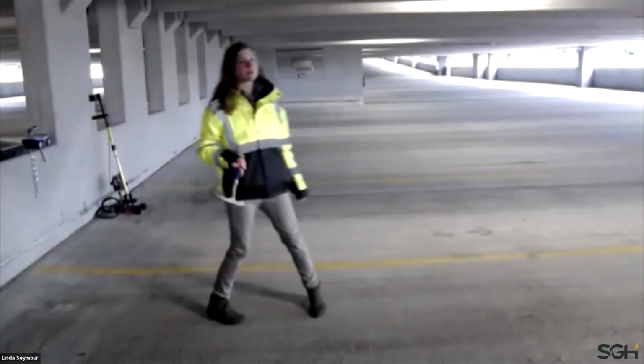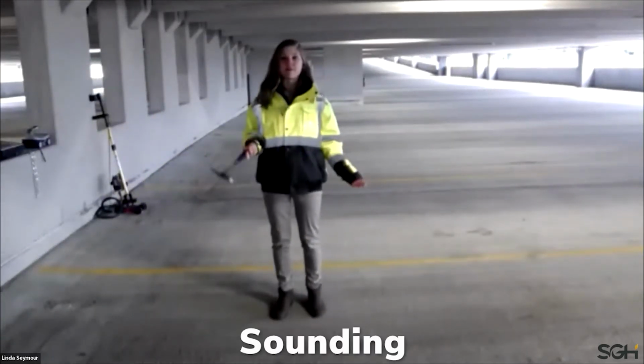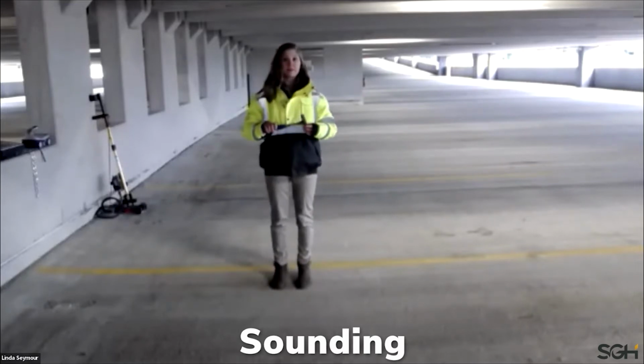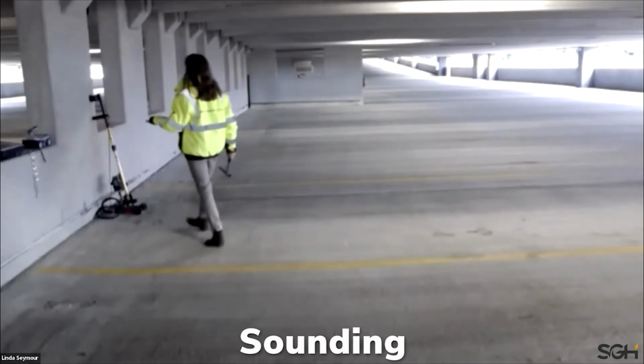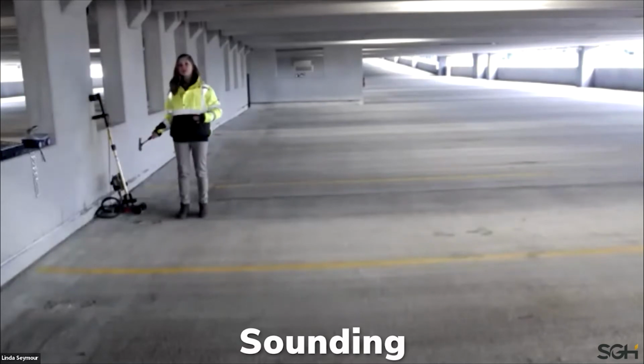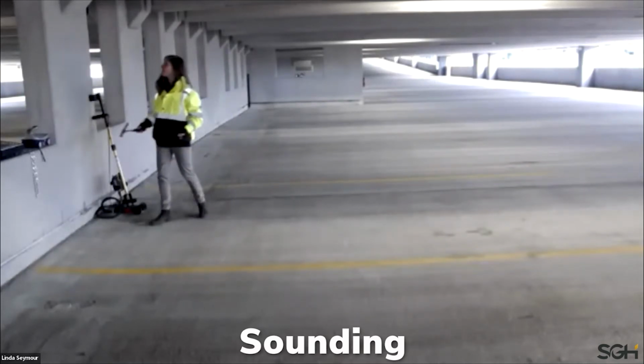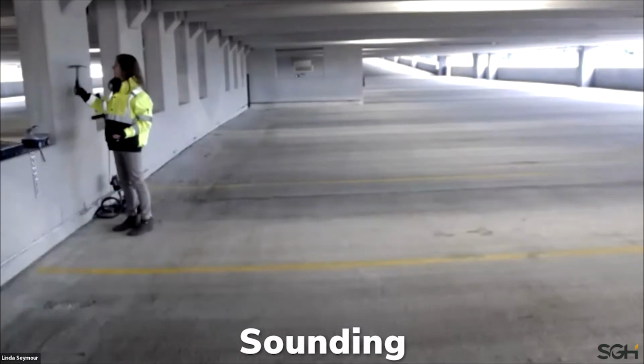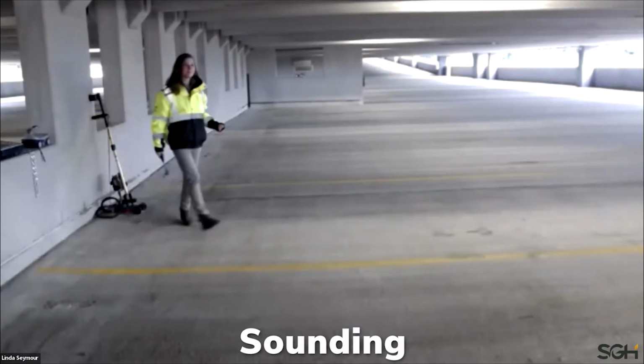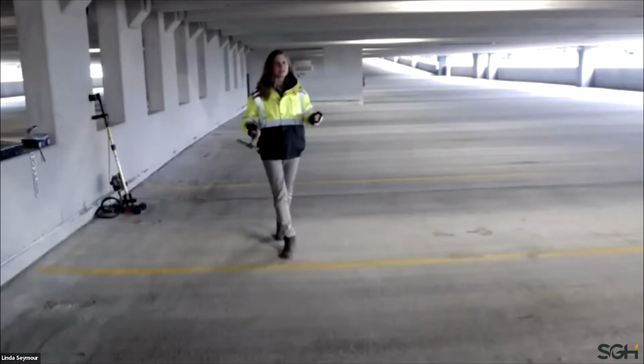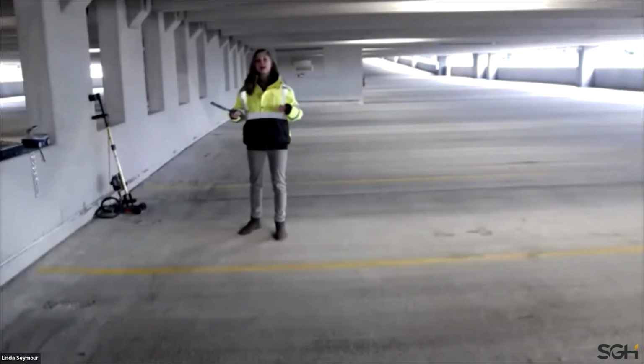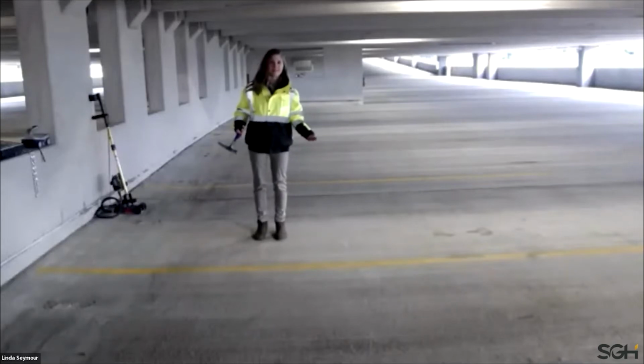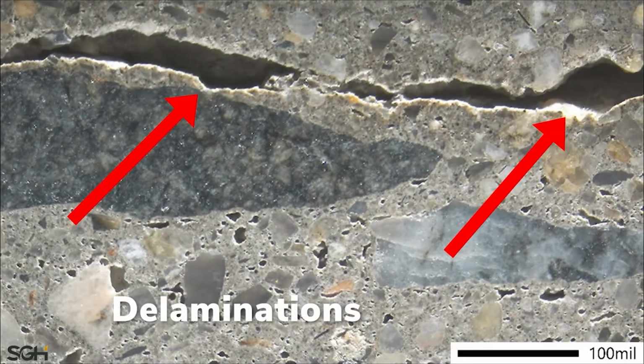One of the first ways we're going to do this is through a technique called sounding. We're going to take a hammer, such as this one, and go to the concrete where we possibly see distress and expect there to be an issue. And we're going to hit it. Bad concrete, or concrete that has distress present, is going to sound more hollow than concrete that doesn't have deterioration present. One of the more common signs of distress that we're going to find with the sounding technique is delamination, or when layers of the concrete have started to separate.